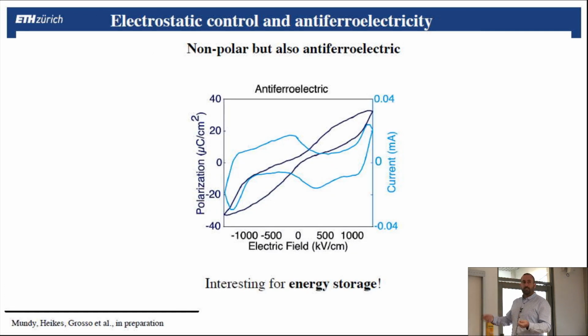And I'll just conclude with this. So an interesting property of this, or the initial motivation, was to create antiferroelectrics from a ferroelectric material. And what I'm showing here is the hysteresis loop that was experimentally measured for the system, and is maybe not so clear, but it's actually characteristic from an antiferroelectric material. And it's then a good way to have this antiferroelectric material not based on lead and having an interesting energy storage.